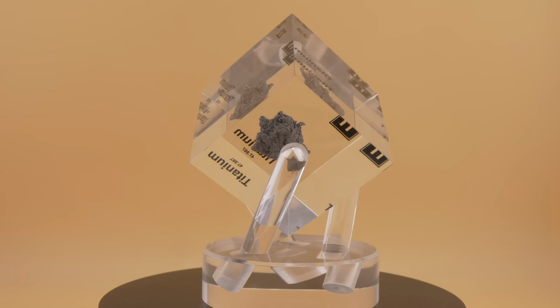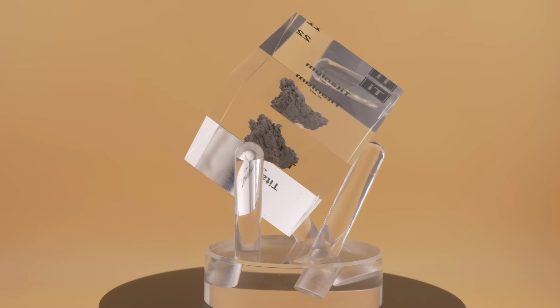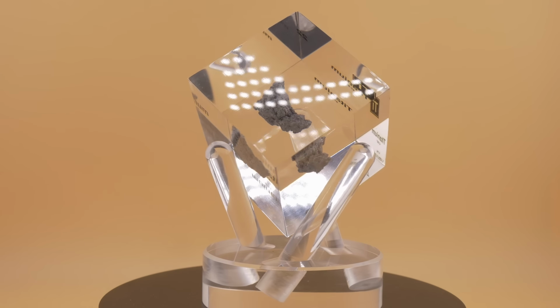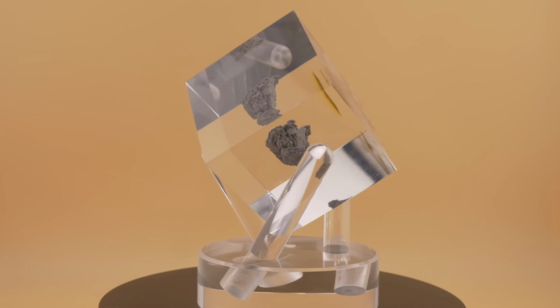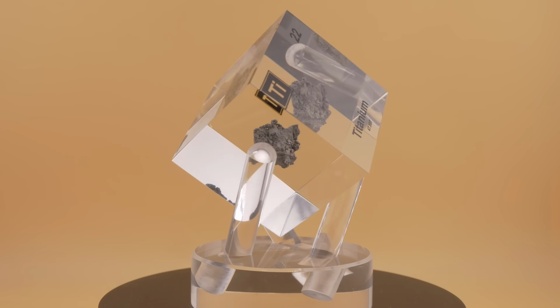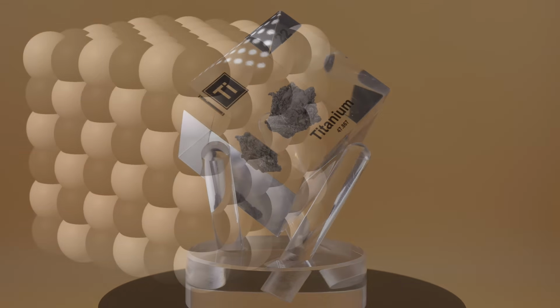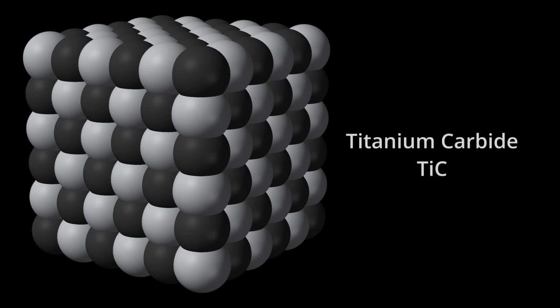Traditional metal extraction methods, like using charcoal to reduce ore, which works for iron, failed for titanium. Now, if you try to extract titanium from its ore using carbon, like you would melt iron, the titanium grabs the carbon and forms a hard, brittle compound, titanium carbide, instead of pure metal. This affinity for carbon and oxygen made titanium extraction tricky.